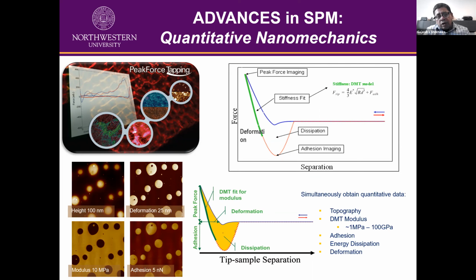Okay, so this is very popular. Here we modulate the probe at 1 or 2 kilohertz, which is well below the resonant frequency of the cantilevers. And the advantage of this technique is that you can look at the force-separation graph. You can see here we can quantify a lot of things. You can do adhesion measurements. You can do energy dissipation, which is basically the area under this loop if you have adhesion. And then you can also do the deformation, how much the sample has been deformed.